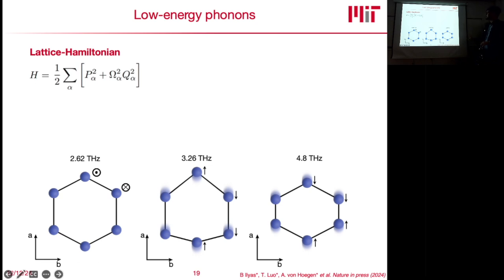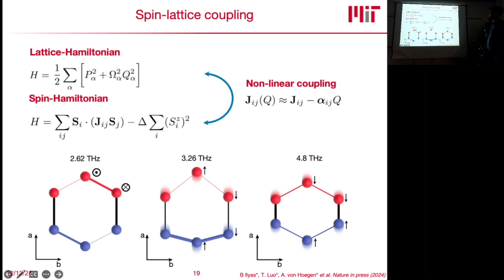They calculated the low energy phonons, and these are the phonons in the relevant spectral range. Here this means out of plane, in plane, and the arrows indicate in which direction the atoms are moving. In this specific case, which is the mode that people have identified as the magnon-phonon, we see that one of these chains is more buckled and this one is a little bit straighter. Here, the chains stay the same but are moved closer together. They then added this nonlinear coupling, this phenomenological coarse-grained coupling term, where the exchange interactions are linearly modified by our phonons. All of these indices ij just mean these are different phonons.